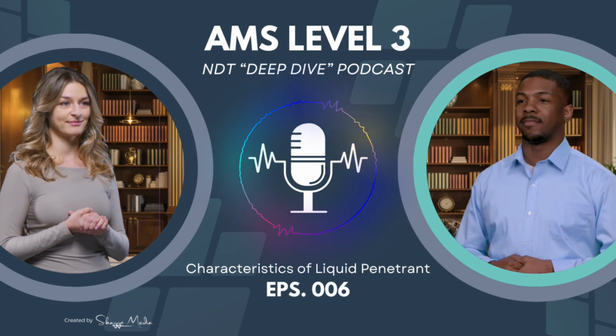That's where viscosity comes in, right? Its resistance to flow. Precisely. Viscosity dictates the rate of filling. Now, for most of the defects we're looking for, the actual length of the void is really small. So usually the filling time is just a matter of seconds, unless, of course, the penetrant is incredibly thick, really viscous. Which you might think gives you more control, but maybe not. Well, high viscosity can cause practical headaches. One big one is drag out, basically, wasting a lot of penetrant because it clings to the surface too much, and it just slows down the penetration time, which isn't great for efficiency in a production environment.